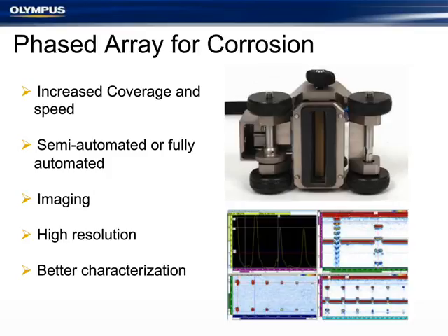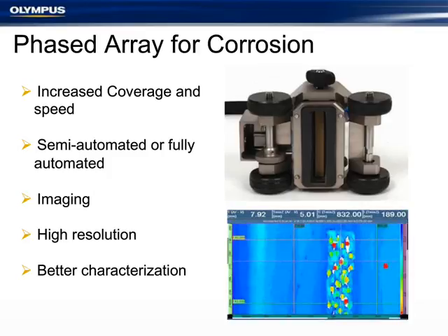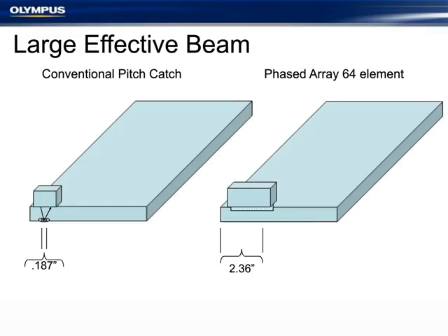And then we can go there, just a large image of both a mid-wall anomaly shown here, all the light blue being basically good wall, and then a very big corrosion cell with different pits. And once we have this data, again, we can manipulate the data very quickly because it's all digitally captured. We can look at it in an infinite number of ways. So just an infographic or a visualization of that.